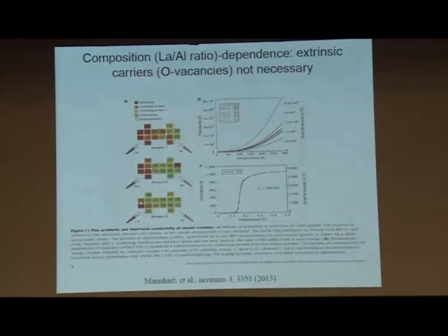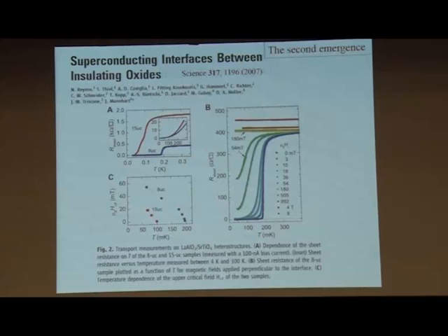So this is one of his 154 samples, out of which he chose 54, and these experiments were done. It's actually a very thorough set of data. Okay, so the second emergence was the superconductivity at the interface, and this was really striking because you can even have a superconductor to insulator transition without going through the metal as a function of both gate voltage and magnetic field. The TC critically depends on the number of layers. 8 seems to be a very good number for highest TC.